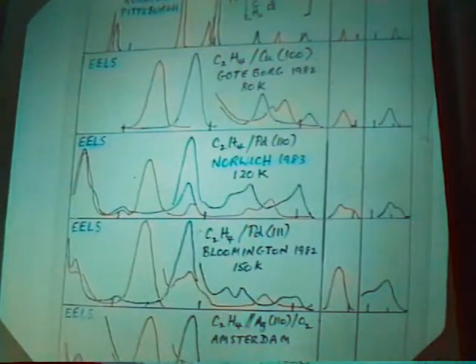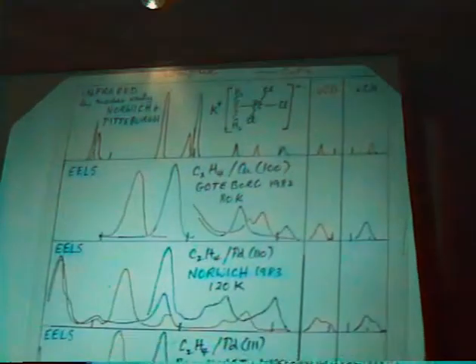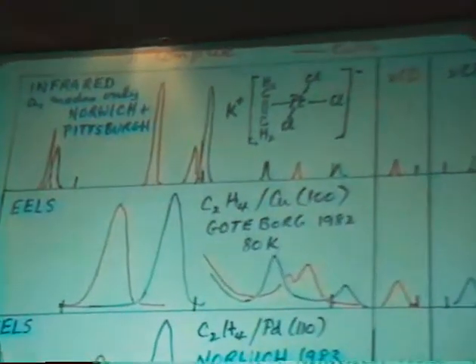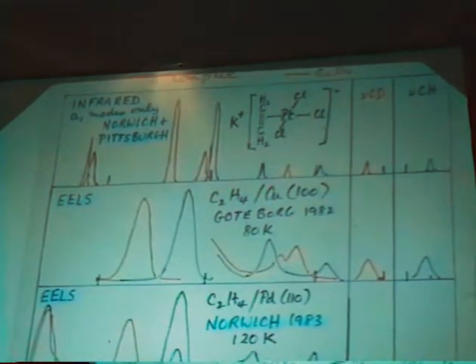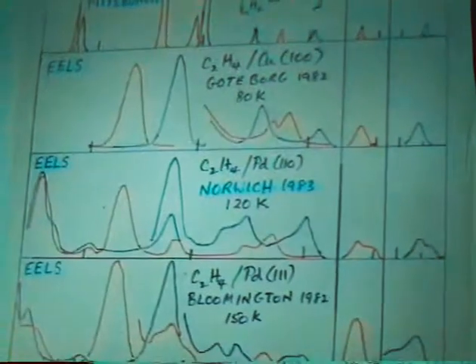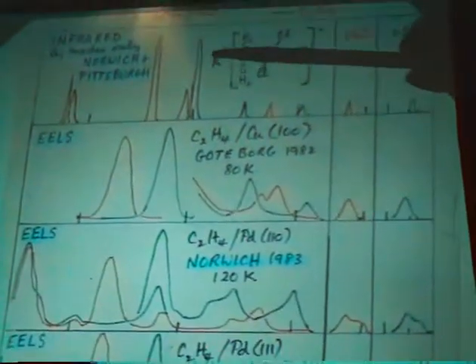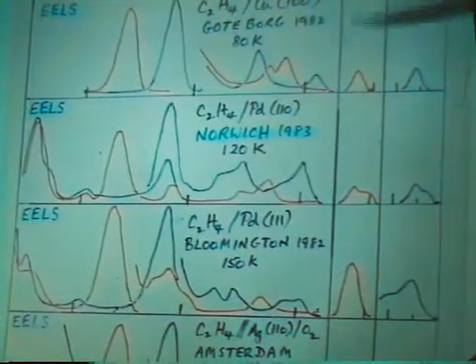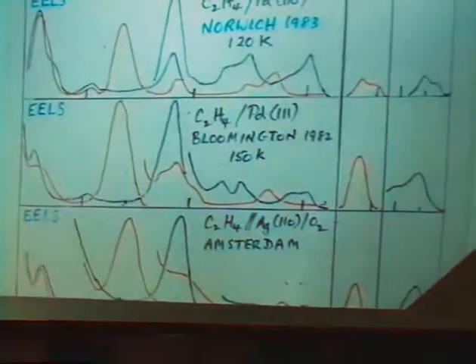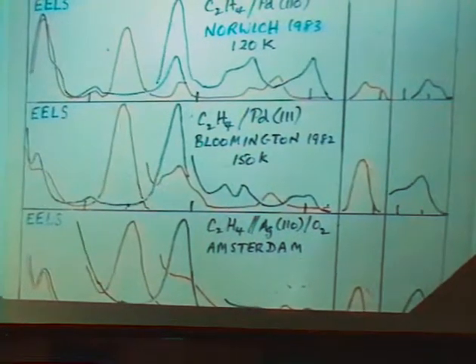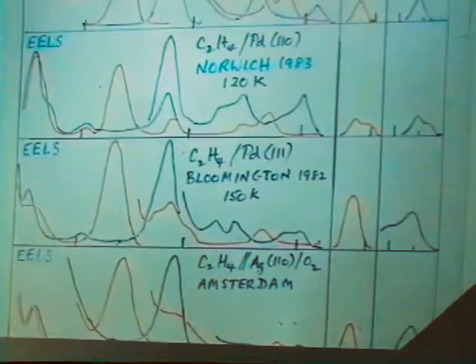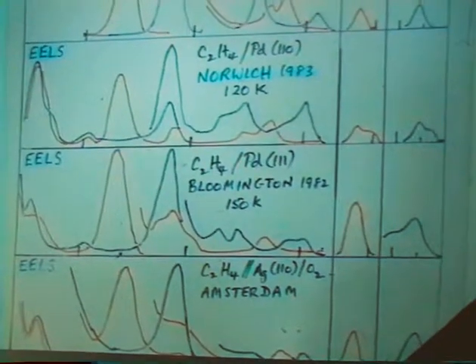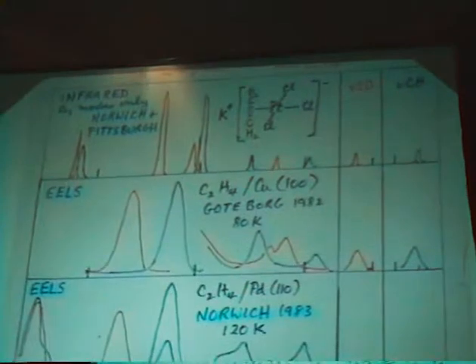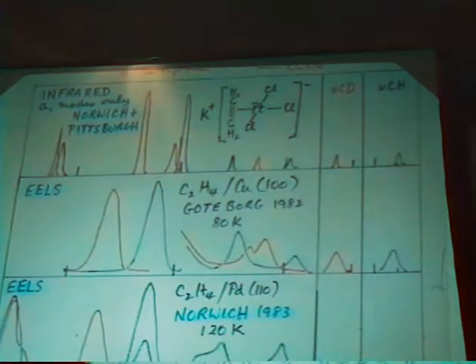And of course, for the pi complex, everybody used the famous Zeise's salt. And this is, again, just the perpendicular modes for Zeise's salt for a pi-bonded molecule parallel to the surface. And these are the actual spectra. Now here you can see that there is a definite shift as you go from the model compound to the other compounds, which are internally very consistent themselves, but there's not much doubt that the pattern is exactly the same. And the reason for the shift is actually not hard to find. You've got three strongly electron withdrawing chlorine atoms around the platinum, so that it's the model compound this time which is very atypical relative to a metal surface. But we can pick out the pi complex on quite a few different metal surfaces of different configurations.